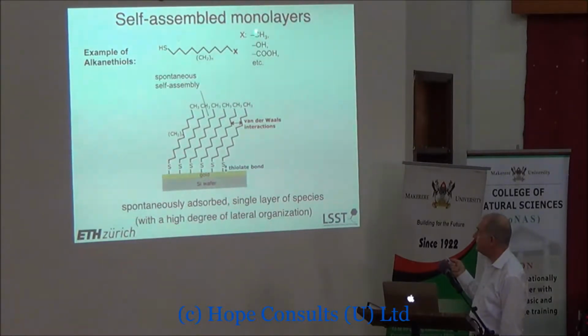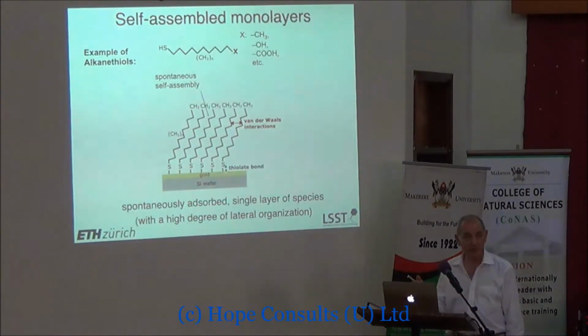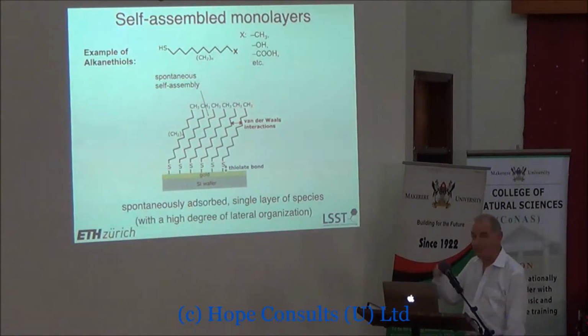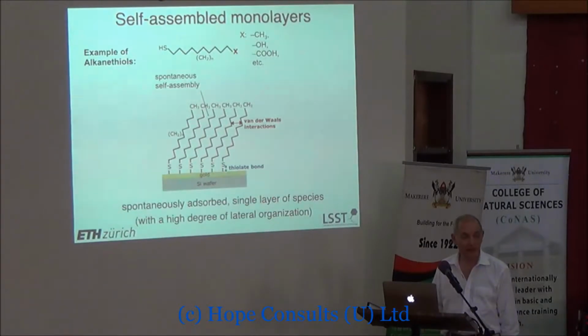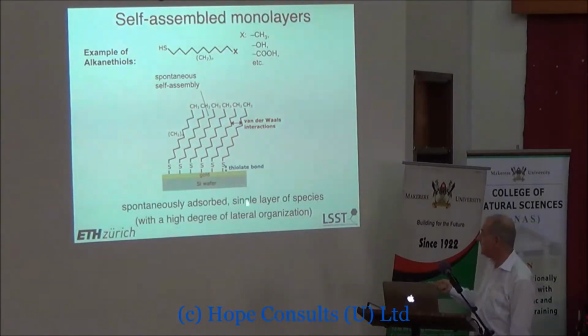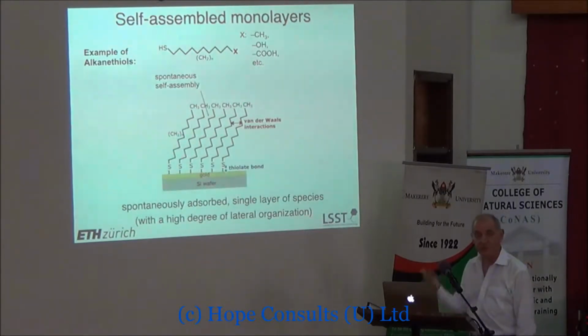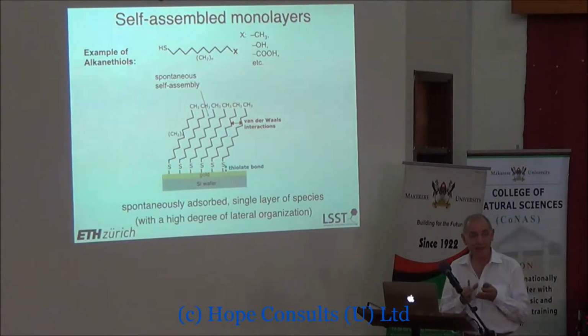So let's say we pick the CH3, and we take a lot of these molecules and we expose them to a gold surface. This isn't pure gold. We just evaporate a layer of a few tens of nanometers or hundreds of nanometers onto a silicon wafer. And if we dip that into a solution of this thiol, then the thiol automatically sticks down onto the gold. It's a very strong bond it makes to the gold spontaneously. And these chains interact by van der Waals interaction, and they lead to a kind of packing that means the whole thing becomes spontaneous and very crystalline.